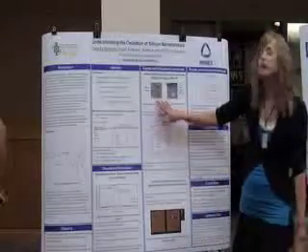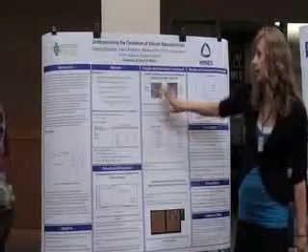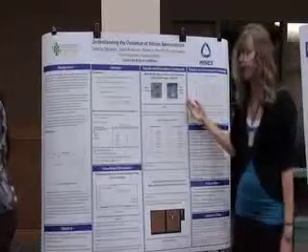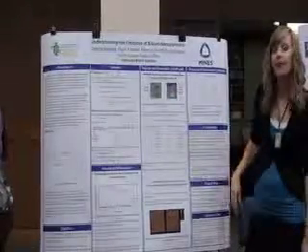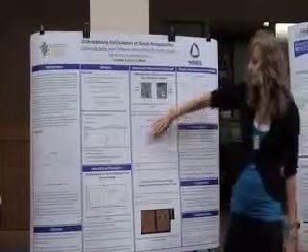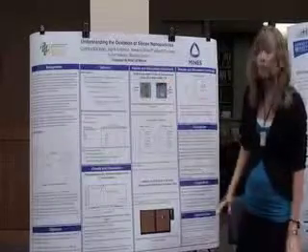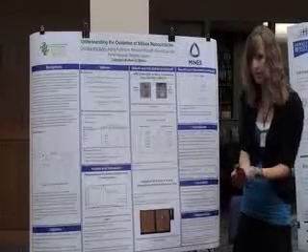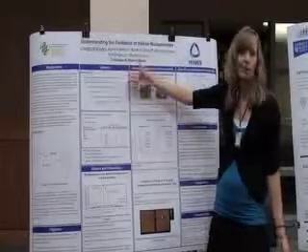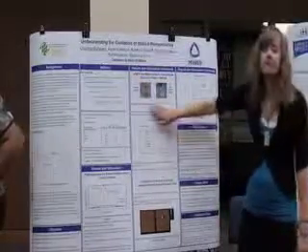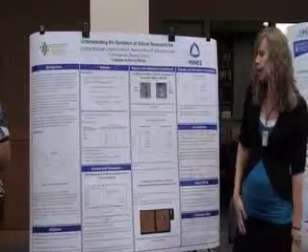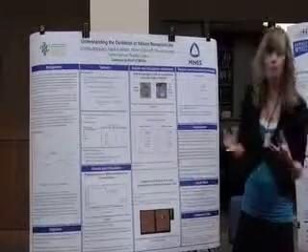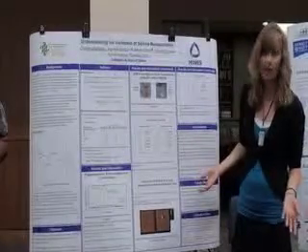We also found that there is a large difference in the particle size of nanoparticles that have been exposed to air prior to going through these steps and nanoparticles that had not been exposed to air. So you see these images, there are differences in the color as well as differences in the size of the nanoparticles in those solutions. The only difference is that these nanoparticles were taken out of the reactor, exposed to air, so they can grow the silicon oxide on the surface, and then they were washed with ethanol and DCM and then oxidized. And these are both exposed to the same concentrations of nitric and hydrofluoric acid, whereas these, they went straight from the reactor into the washes. So they didn't have that native oxide, which is one of the main differences we saw. And it's just a difference in the character of the oxide.